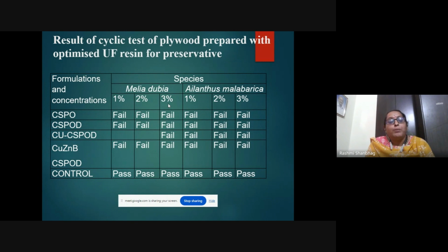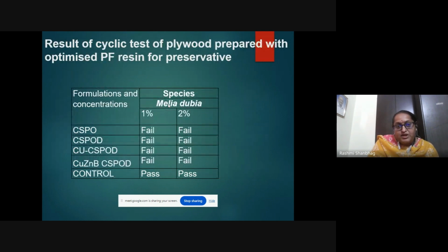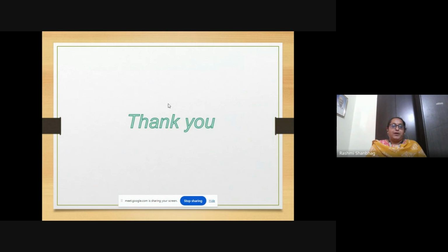In case of plywood, what makes the difference is that if the preservative mixes properly with the resin, only then is it considered a good preservative. We used Melia dubia and Ailanthus malabarica for the preparation of the plywood, as these are the two major species used in plywood preparation. We found that this material was not compatible enough with the glue line. In case of UF resin as well as PF resin, this particular preservative was not compatible.